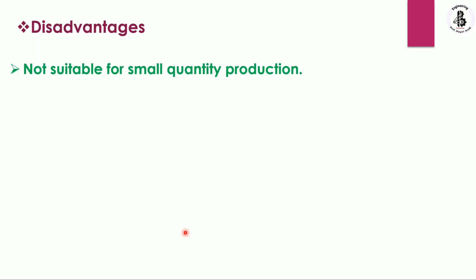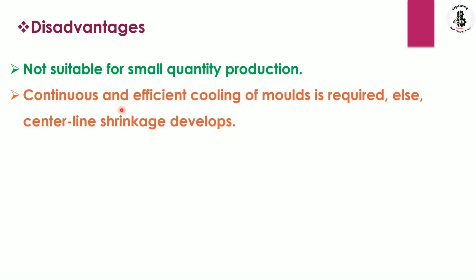Some limitations or disadvantages: it is not suitable for small quantity production since it is designed for continuous, high-demand output. Continuous and efficient cooling of the mold is required, otherwise centerline shrinkage develops. It also requires large floor space due to the continuous process from molten metal to finished product.